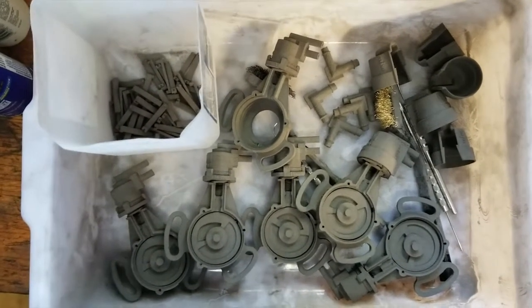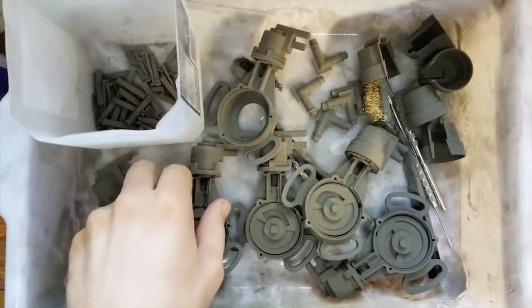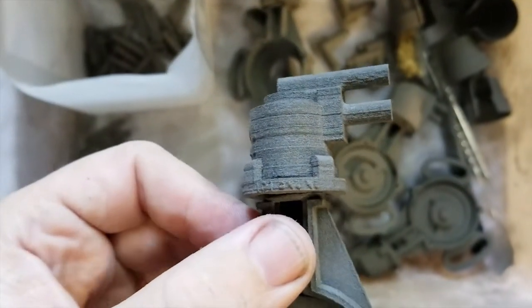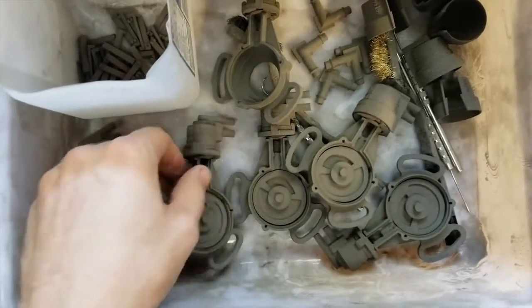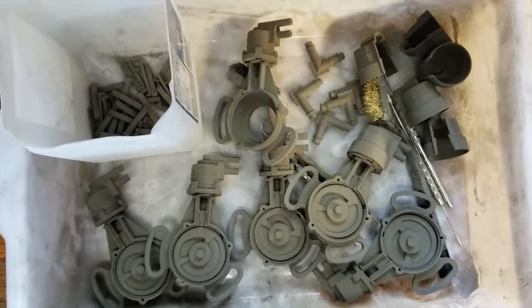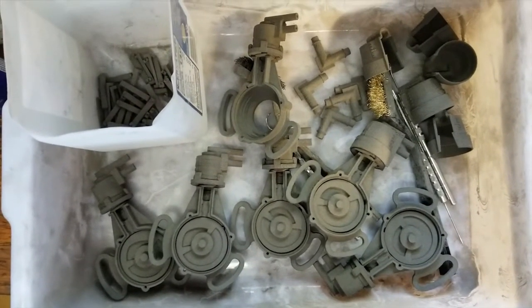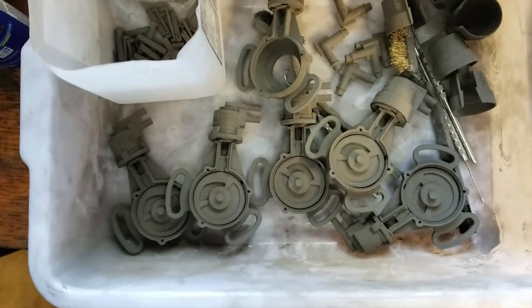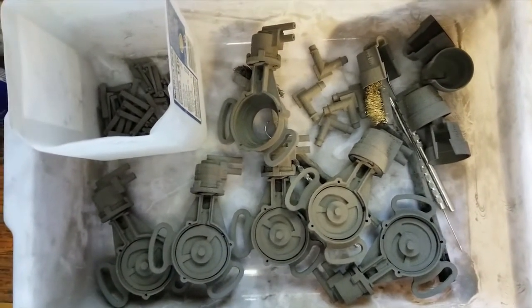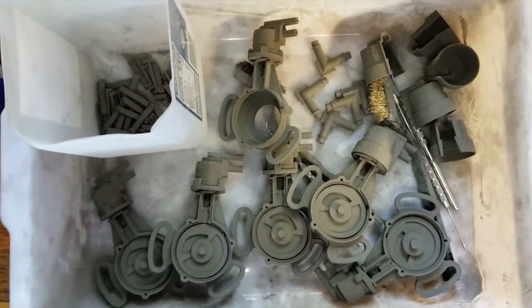This is a really good sign — the quality is really good. I had a few spots where I had some lines, and that was at the very top. I think my galvo is off. Otherwise, most of this is pretty outstanding, and I didn't get any fusion. I was worried because I had the temperatures up to 173.8°C near the end, and there was no fusion of the powder. It just worked out great.